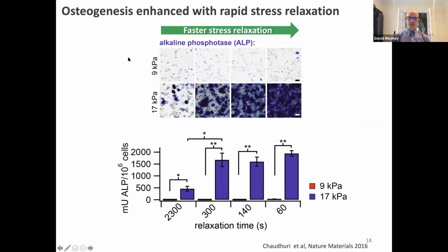So for example, if we took these cells and put them in a really soft gel, very few of the cells would become bone-forming cells, as indicated by the lack of blue staining. If we put them in a modulus that was permissive for them to differentiate to become bone-forming cells, we got more and more differentiation as the rate of relaxation became more and more rapid. So the interplay of the modulus and the stress relaxation was dramatically important in controlling the fate of these cells.